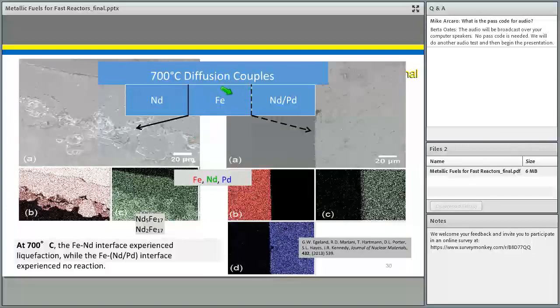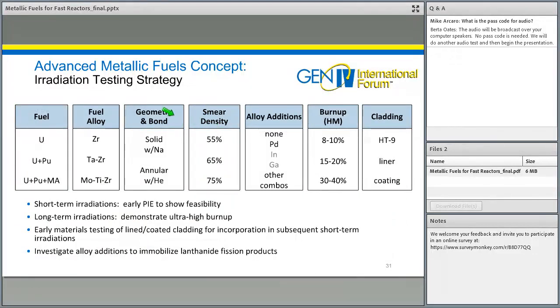This is what you get as a result of FCCI. But what we did is we looked at a couple where iron was put against neodymium with the addition of palladium in the one-to-one ratio. And not only was there no interaction at 700 degrees C, not only was there no liquefaction, there's essentially no interaction under the same conditions, 700 C and 100 hours. So that gave us a lot of hope that a palladium addition could be beneficial for this problem under irradiation.